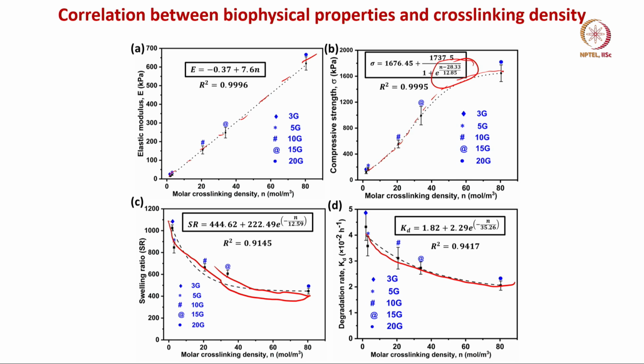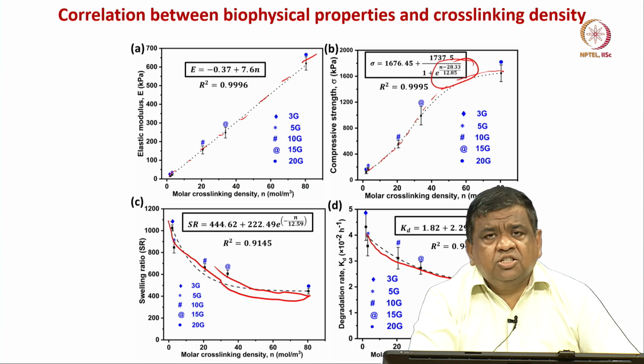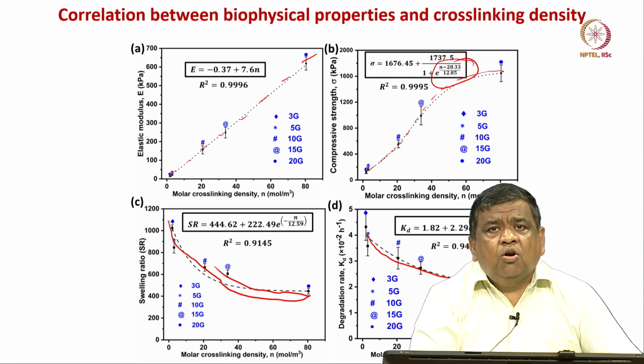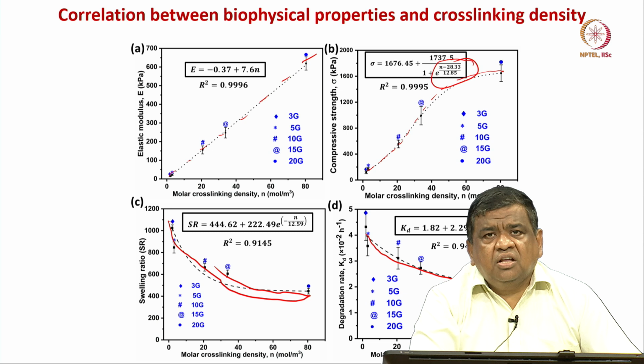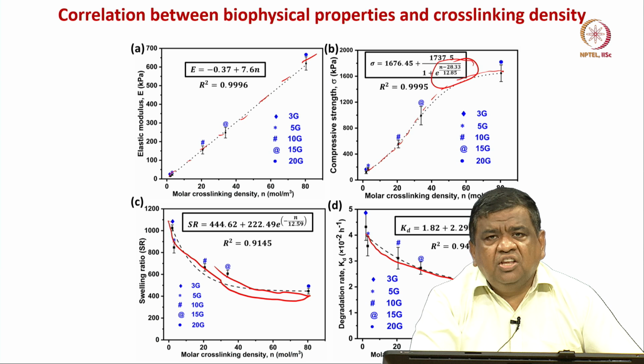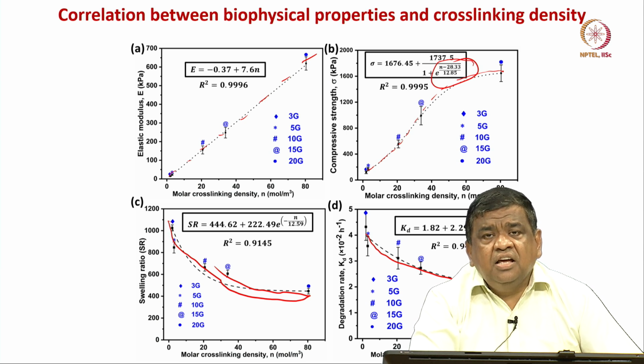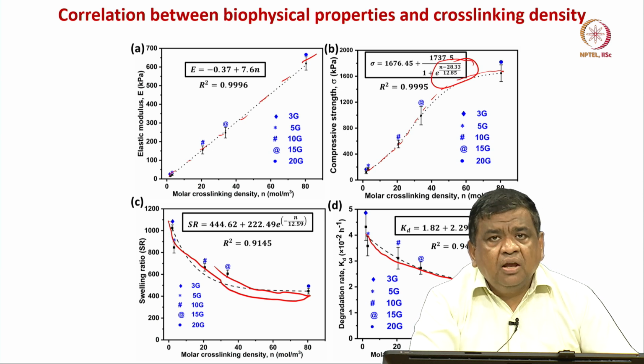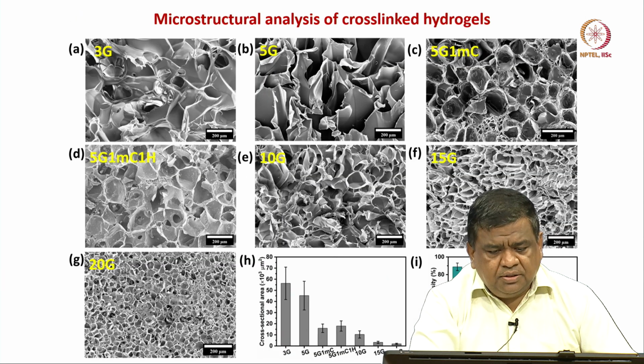Now, all these four properties are clearly dependent on the molar cross linking density, and that is the way one has to analyze these GelMA properties. So, often you will notice in research papers or publications, people always put the GelMA concentration on the x axis. That is not correct, because the physical properties which will influence the strength and elastic modulus and so on must be some physical properties, and as has been identified here, it is the molar cross linking density, that is the parameter which influences all these properties.